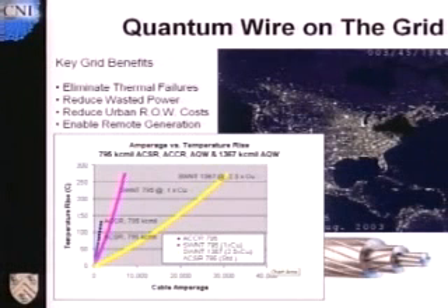And so there are a couple of key applications. One is in reducing the power dissipation in long-haul transport. And another one is to improve the amount of power you can actually get through high-density urban corridors, where the right-of-way cost can run $100 million in, say, the periphery of an urban area. And so this is a material. This is an ACSR cable. It has a steel core and then aluminum conductors on the outside. We use that as a baseline. This particular one is 795 circular mils of conductor. And this is basically how much current you can put through it before it gets up to a 75-degree centigrade temperature rise.